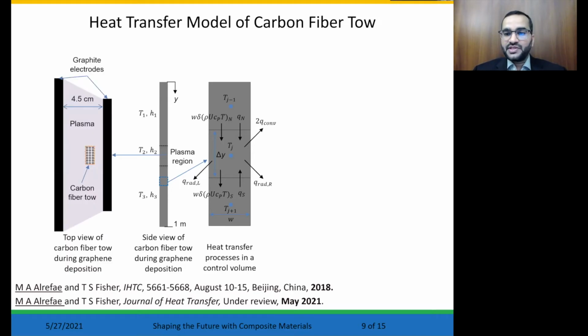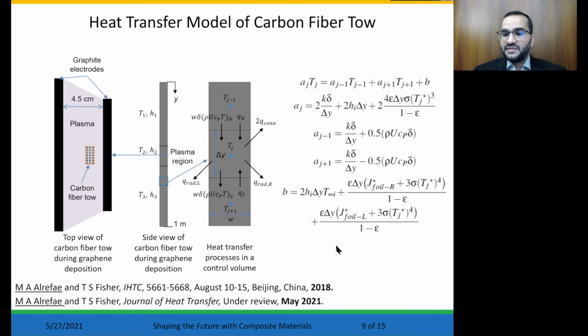The carbon fiber tow consists of a few thousand individual fibers, which makes it challenging to model these single fibers individually. Instead, these single fibers are lumped into a tow, which can be modeled much easier. The tow was under tension during the roll-to-roll process, causing the tow to flatten out with an approximate rectangular shape. The cross-sectional dimension of the tow is around 1 millimeter by 2 millimeter, which was measured while applying tension in the roll-to-roll setup. So the temperature distribution was solved numerically in MATLAB.